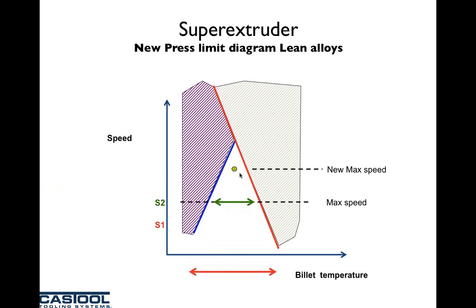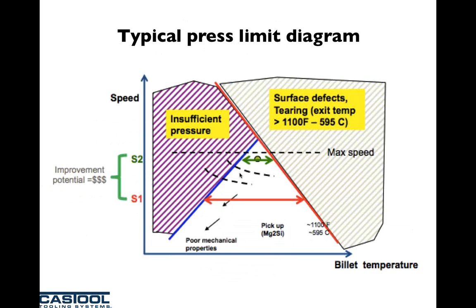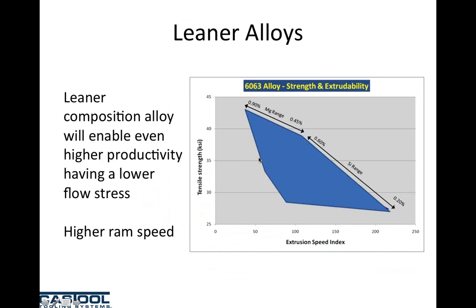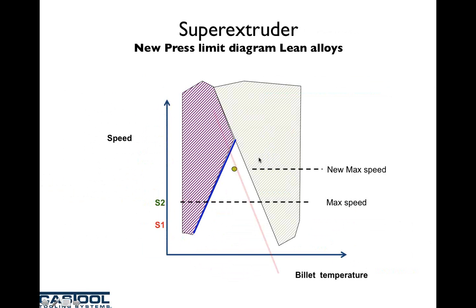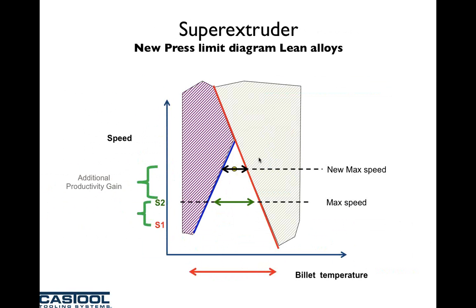Boy, this is a complicated one. Again, we had a rather wide triangle here, and the average extruder is trying to get up to this point. And then we take our super extruder, and we change all of the rules. And by that, we're seeing ram speeds about 40% faster than the average extruder.